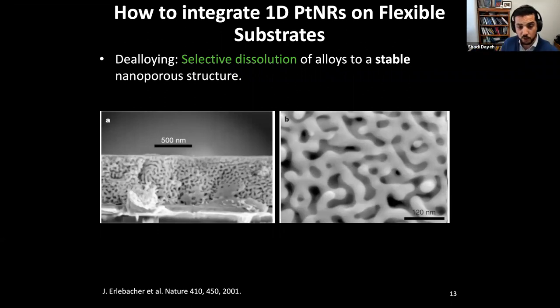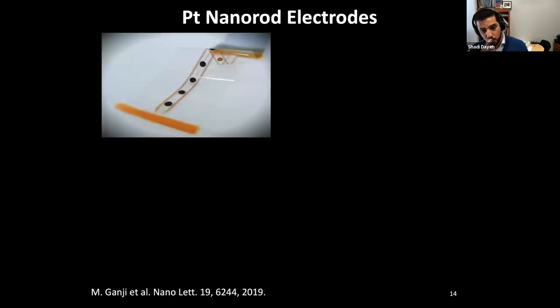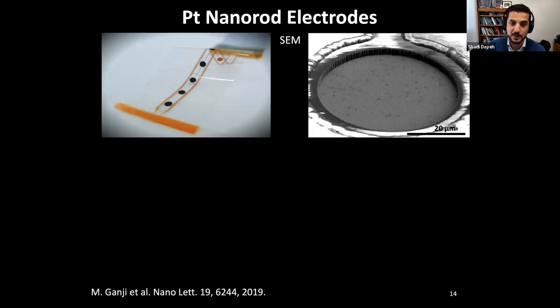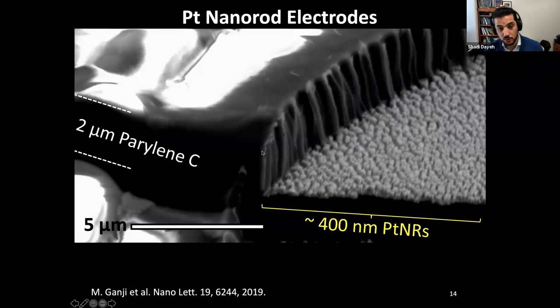So we tried it for platinum and we were able to tune it to have a nanoporous structure or a one-dimensional structure. We used the one-dimensional structure in this work. This is a scanning electron microscope image on the right of how these contacts look. Maybe we look at the cross-section to see it a little bit more clearly. At the bottom of this mesa, we have a forest of nanorods.